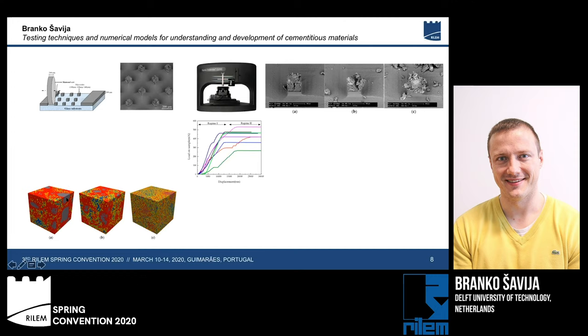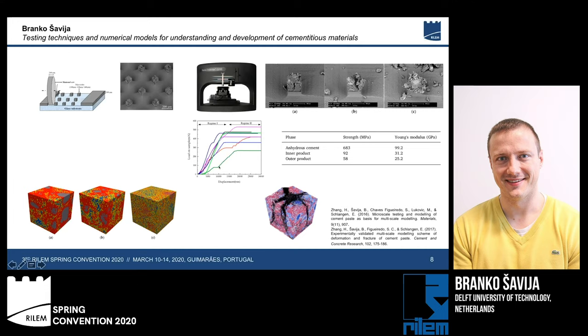And then we can subject these microstructures to the same types of loads that we have done in our experiments. And by inverse analysis, we can set the properties of our microstructural phases, unhydrated cement, inner products, and outer products, in such a way that we can mimic the global behavior of our microvolume. So now we know, as we knew already from nanoindentation, the Young's modulus of different phases. Now we know the strength properties in our hydrated cement paste.